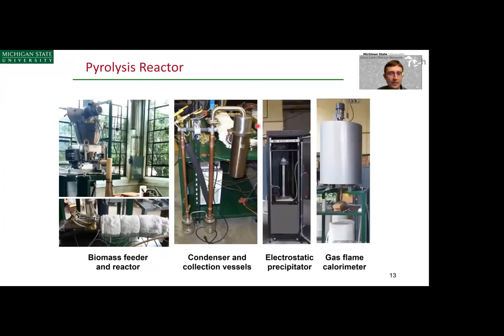You can see the feed hopper here on the left, the reactor barrel on the bottom. This is the char trap and the 2 condensers. We collect our bio-oils in ball mason jars. This gas then goes overhead to an electrostatic precipitator, and then below this electrostatic precipitator is another ball mason jar. This gas then goes over into a flame calorimeter, and we can measure the energy content with that device.